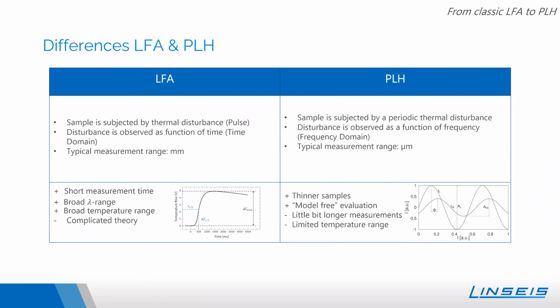But what are now the main differences between the LFA and the PLH? In both cases, we subject our sample to a thermal disturbance. But in the case of the LFA, the sample is subjected to a short, high-intensity laser pulse. On the other hand, in the new instrument, the PLH, the sample is subjected to a periodic thermal disturbance. Furthermore, this disturbance is then observed as a function of frequency, which means the evaluation is in the frequency domain.